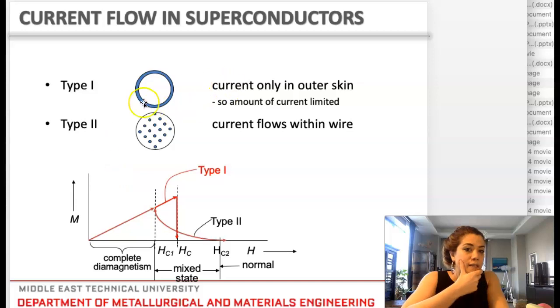So the reason for that is the superconducting behavior for type 1 is only occurring on the outer skin of the material. So this transition occurs really rapidly. But in the case of type 2 materials, the superconducting current is flowing throughout the wire, so over the whole cross section. That's why it slowly loses its superconducting behavior as we increase the applied magnetic field.